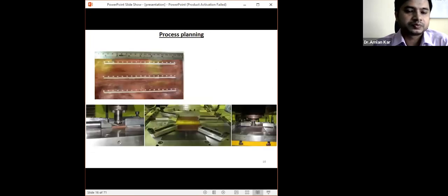So then the objective is how you can overcome this problem. This problem can be overcome, we can see in this process. So here the polymer particle, what we are getting, is directly incorporated into the matrix material. You can see this is the matrix material, copper, and the polymer. You are cutting a groove, and on the groove the polymer particle has been filled. After filling the polymer particle, you do the friction stir process, whatever we used to do, that has been conducted. Since the polymer particle has very low fracture toughness, it does not wear out the tool material very easily.